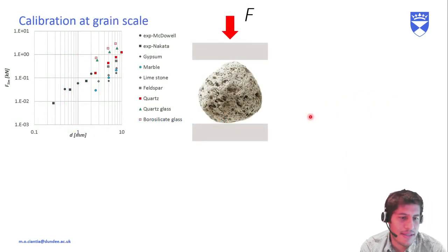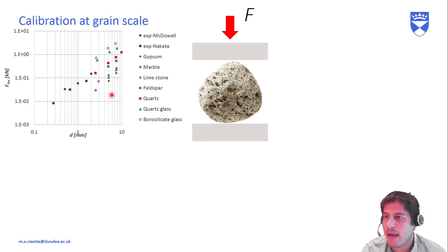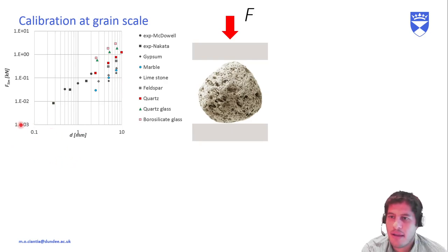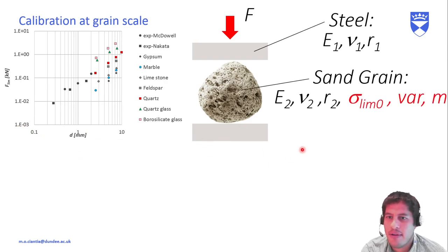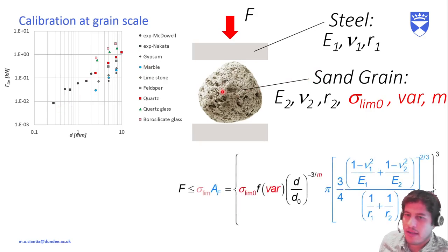We wanted a model that could be calibrated at the grain scale in an easy way. If you do single-grain crushing tests — compressing a single grain between two metal plates — you can plot the data as a limit force against the particle diameter, and you see a typical trend also known as scale effects, where the strength is a function of particle dimension. Our failure criterion has three parameters to calibrate: the strength, the variability of this strength within particle size, and the Weibull modulus.